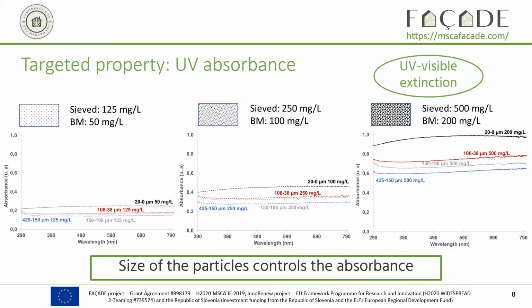In this project, the FACADE project, the targeted property is the UV absorbance. Once we produced biocarbon at different temperatures, with different heating rates, with different residence times, we analyzed all these carbons. And for the same particle size, we didn't see any influence of the process on the absorbance. So the process did not have really an influence on the UV absorbance.